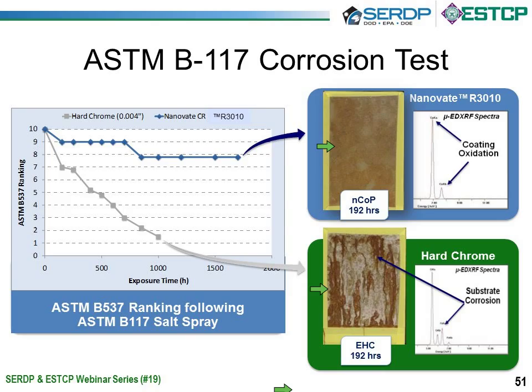What we're indicating in these illustrations to the right of the photographs are whether or not we have iron or base metal exposure from doing an X-ray fluorescence spectrometry test. And we have basically cobalt observable in the upper one, and down below in that spectrum, it's predominantly chrome from hard chrome plating and then iron substrate.